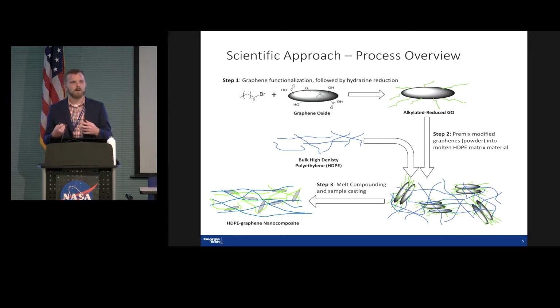Graphenes are light powder, so when working with them, you have to be careful about breathing them. So before we dump these into an extruder, just to be on the safe side, I pre-mix them in some polymer matrix. So you get this very aggregated, very heavy intermediate product, and then we can take that and put it in an extruder that we put on a recirculation loop, and that will hopefully end us with a nanocomposite with well-distributed graphene disks.